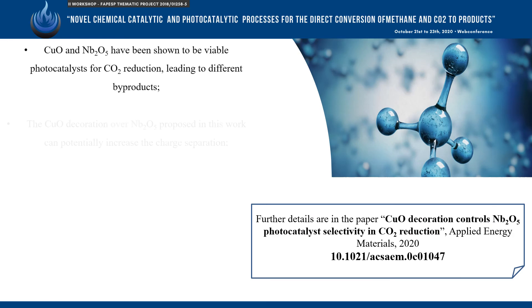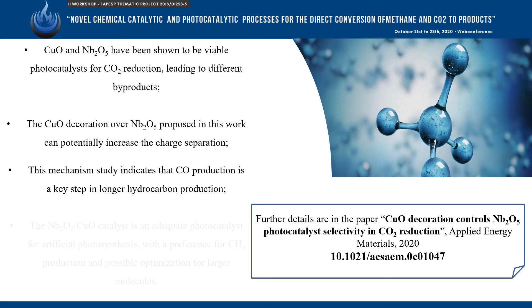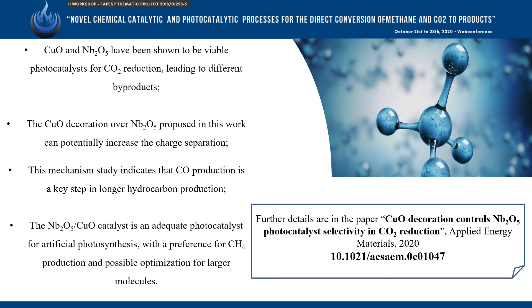Copper oxide and niobium pentoxide have been shown to be viable photocatalysts for CO2 reduction, leading to different by-products. The copper oxide decoration over niobium pentoxide proposed in this work can potentially increase charge separation. This mechanism study indicates that CO production is a key step in longer hydrocarbon production. The niobium pentoxide/copper oxide catalyst is an adequate photocatalyst for artificial photosynthesis, with a preference for methane production and possible optimization for larger molecules.